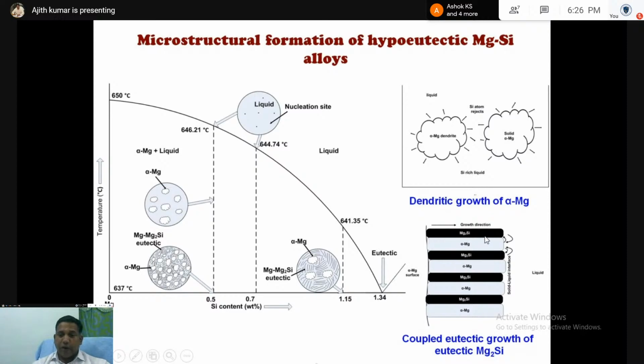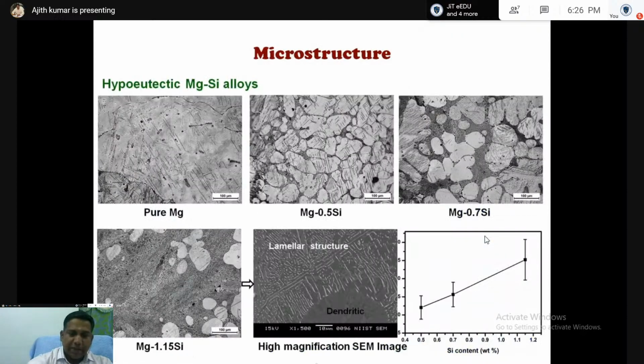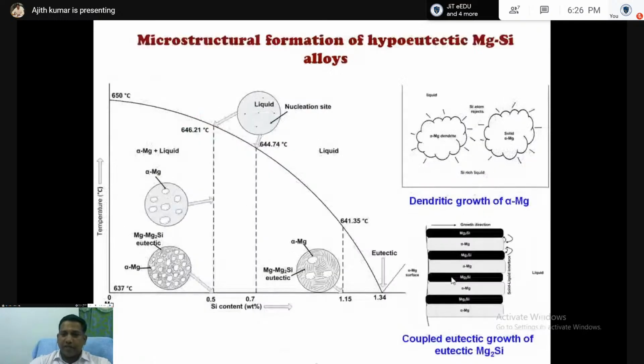This eutectic is forming, we already see in the picture, this lamellar structure. This lamellar is formed because one Mg2Si phase line will form. Surrounding the Mg2Si phase line, the silicon content or silicon atoms are minimum. So in between that region, alpha Mg will form. So this is called the coupled eutectic growth.